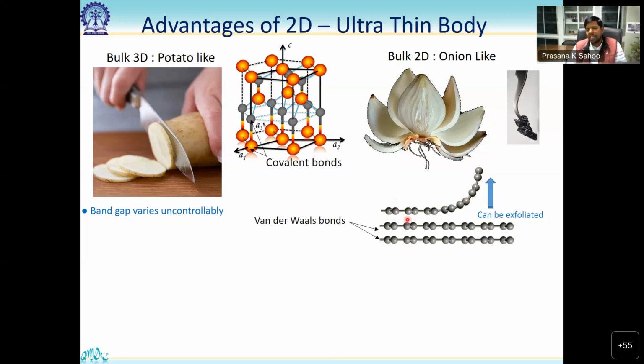But between these layers in graphite, there are van der Waals bonds, because there is no strong bond. Van der Waals bonds are weaker. We can see that they are short range, of order r to the -6, whereas in covalent crystals, the bonding within each layer is very strong. So that's why Coulomb forces are much stronger than the van der Waals attraction. That's why it is easier to peel off a single layer from layered semiconductors or layered materials.